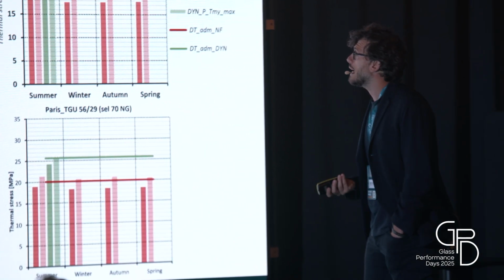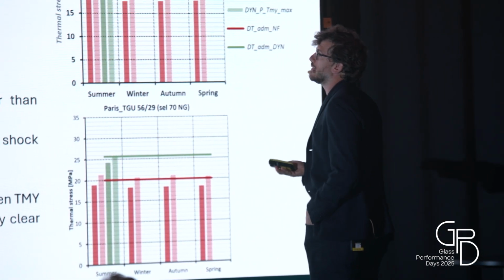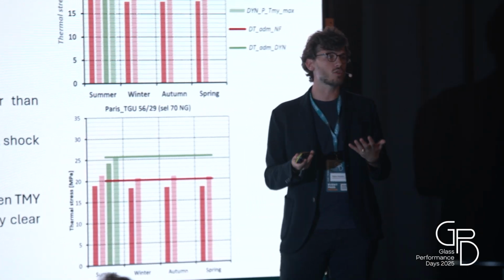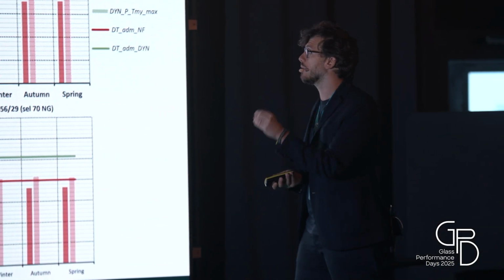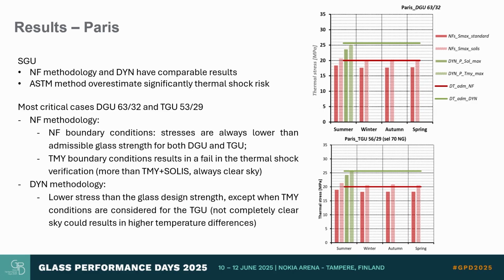So at the end, what we see is that the two methodologies have comparable results, of course, for non-critical cases, but when it comes to the most critical cases, when we use the national standard boundary condition, the stresses are always lower than the admissible glass stress for both double and triple glazing units. While instead, when we use the real sky, the TMY boundary condition, that would result basically in a fail,